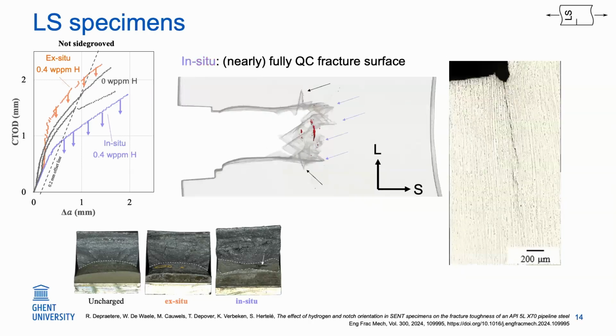For the in situ tests, this is like a combination of all effects. So we have the crack branching, which is very specific to in situ, but we also have these crack arresting splits. And if we look at the cross section, you can see that actually the CT scan captures only the start, and there are much more fine cracks growing along the bands in these specimens.